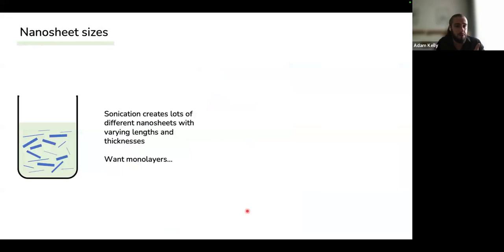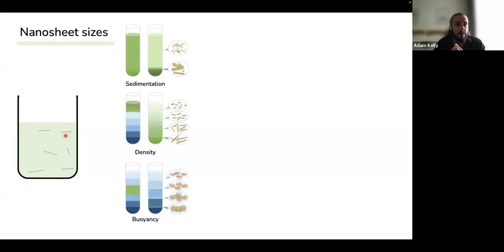So the thing is, once you break up this crystal, you're going to end up with nanosheets of all different sizes and lengths and thicknesses. So the question then is, what do we need to do to screen out the different sizes? Well, there's a number of ways of doing this. One of them is sedimentation-based centrifugation, where we just basically speed up the effects of gravity in a centrifuge, and we run our dispersion. And what will happen is, if you run it at a certain speed, nanosheets that are large, for example, will be sedimented out at the bottom of the vial, and smaller nanosheets will be left up the top.